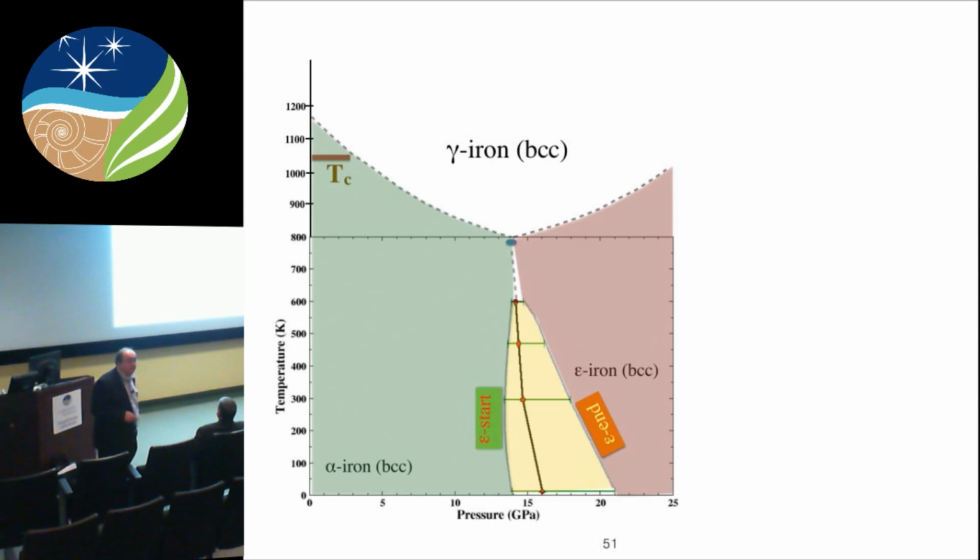Because going back, I learned this the difficult way. Pressure is not like changing the temperature. Temperature you dial and then your crystal starts to go there. Pressure is not like that. It's a one-way street. You cannot come back in the middle of a transition because the instrumentation is not really suitable for changing pressure by 0.1 GPa as you will. Even though we have a membrane cell and we have tried to do it carefully, it's still difficult. So I saw many, many data points that are so different from each other on the reverse side. But I will try, because Ron brought that point up also during our conversation.